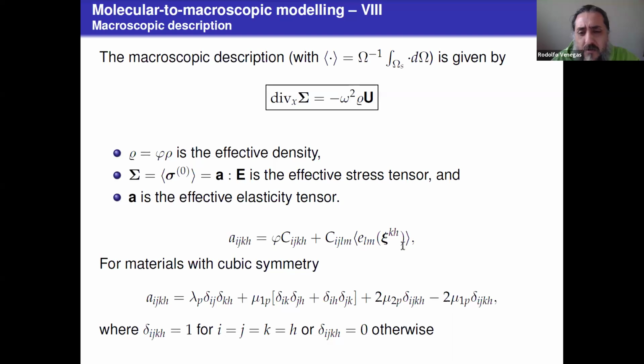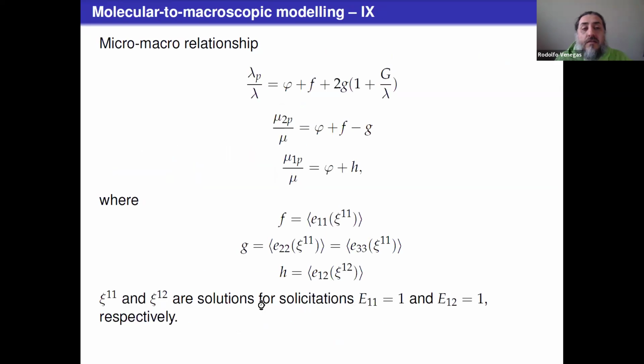That takes this general form. This, in particular, comes from the solution of this problem. And for a material with cubic symmetry, we know that we can write this elasticity tensor in this way, so we can match them and get this elasticity constant related to the Lamé parameters and these shear moduli. So specifically, this is the relationship for the normalized first Lamé parameter and this normalized shear moduli, where F and G depend on the values that we can calculate from the solution of this local boundary value problem,